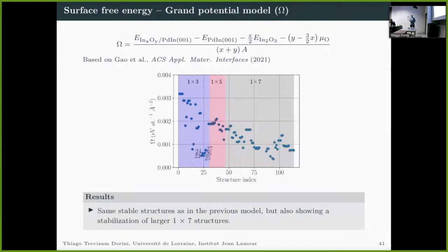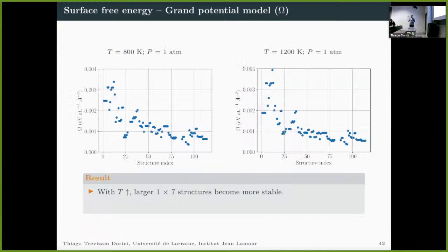So here we have the results using this model. We can also see that the structure that has the lowest interface formation energy also presents a very stable grand potential free energy. And we can see a tendency that the bigger structures are more stable than the smaller ones, the 1/3 and 1/5. We can also see this property when we increase the temperature, where the 1/7 structures become even more stable than the smaller ones.